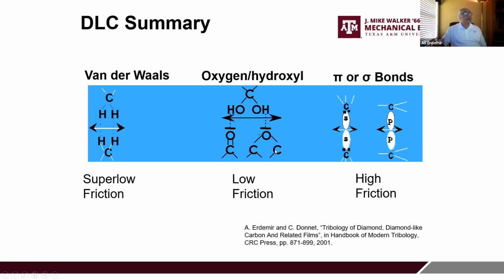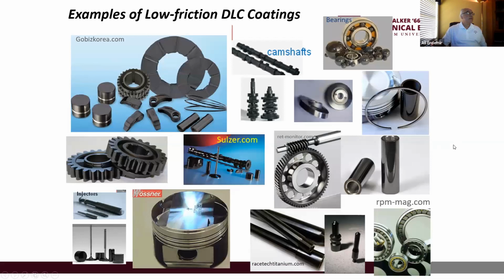friction would be higher. If there's no hydrogen at the sliding contact interfaces, this will be very typical of tetrahedral amorphous carbon that is produced from a carbon target, either by pulsed laser deposition, PVD, or sputtering methods. Those surfaces actually give very high friction, mainly because of these pi and sigma bond or covalent bond interactions. So DLCs actually made a huge industrial impact.